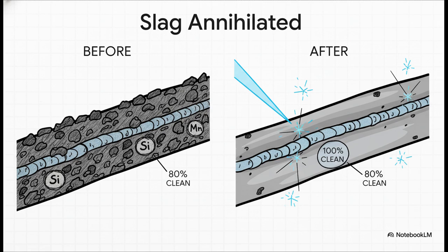And what about the slag? The results here are honestly even more impressive. At 160 watts, the laser completely annihilated 100% of the slag in the center of the weld and still got rid of 80% from the trickier edges. And you can see here the main ingredients of slag, silicon and manganese, have practically vanished.